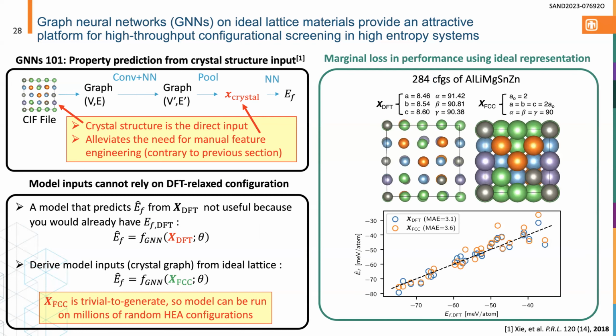There's a DFT relaxed configuration. There's this idealized FCC representation mapped to its ideal coordinates. And when you train a model to predict the relaxed formation energy, using either as inputs, both can predict the formation energy very well. In this case, because there's not a huge rearrangement of the atoms, there's just local distortions, the model is able to accurately predict what that system should relax to based on the idealized input.